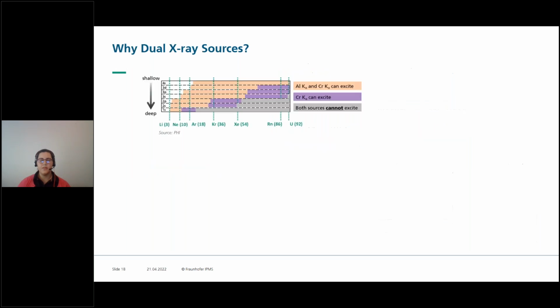So why do we want dual X-ray sources? Here, there is a simple diagram combining a scale of a wide range of elements ranging from lithium to uranium. On the left-hand side, you see core energy levels from shallow to deep states. There is a color coding where the sources can excite, and it's clear that chromium can reach heavier elements and higher binding energy core lines. Both sources, therefore, measure to different energy ranges.